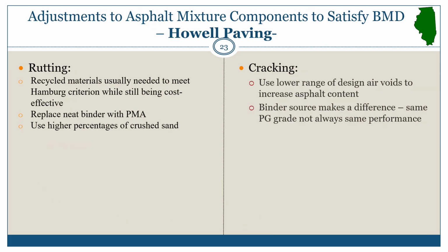Speaking with Pat Koister at Howell Paving, what they have found is that to help meet their rutting requirements, they usually need to add some recycled asphalt. It helps to stiffen up the mix, and they found it to be very cost effective that way. They can replace some of the neat asphalt binder with some polymer modified binder. Going from a neat to a polymer helps to increase the high temperature stiffness of the material, as does using higher percentages of crushed sand.